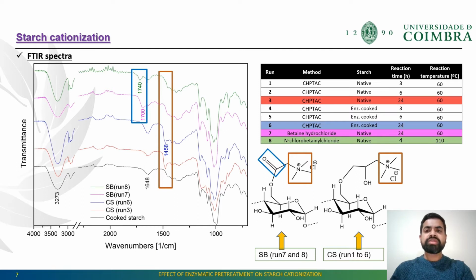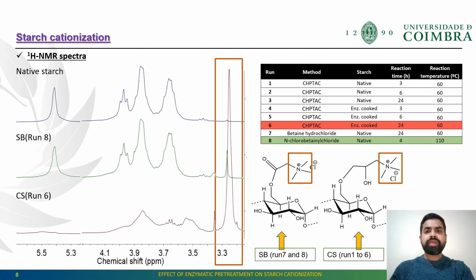All fundamental peaks of starch can be seen in all spectra. Compared to the native starch spectrum, a new prominent peak at 1458 cm inverse can be observed due to the quaternary ammonium group attached to the anhydroglucose unit during the etherification and esterification reaction. Additionally, peaks at 1700 and 1740 were observed due to the presence of the ester bond in starch betainate. In this slide, the proton NMR spectra are shown for cationic starch ether and starch betainate and compared with the native starch spectrum.